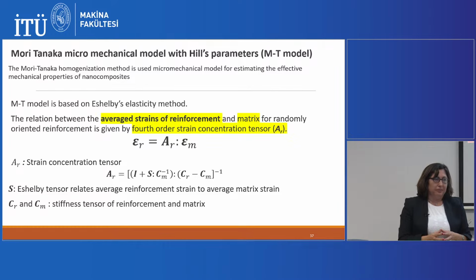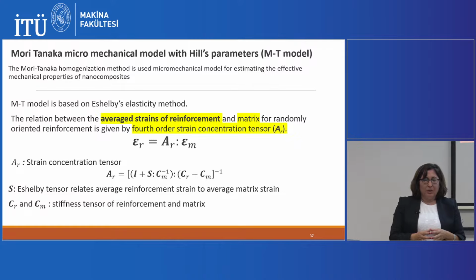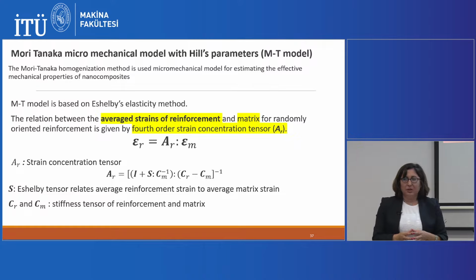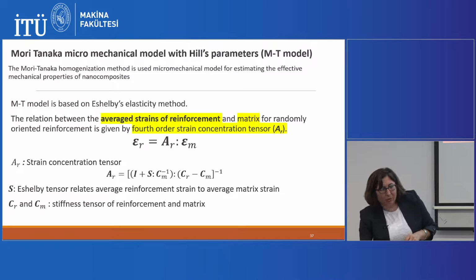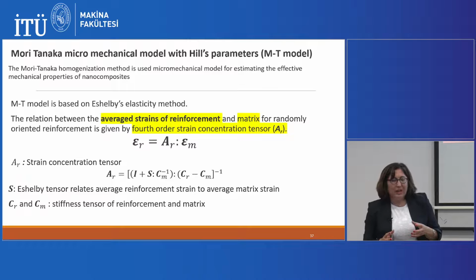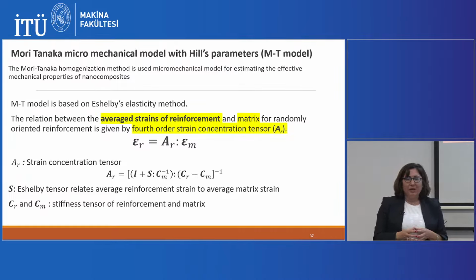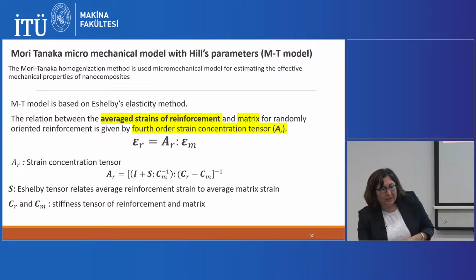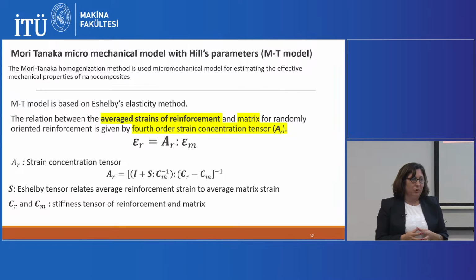Mori and Tanaka defined this homogenization technique, and it involves a lot of math. It defines the relation between the reinforcement and the matrix, and from this Mori-Tanaka approach, we end up with the effective stiffness tensor, and from here we get the effective elasticity modulus. Okay.